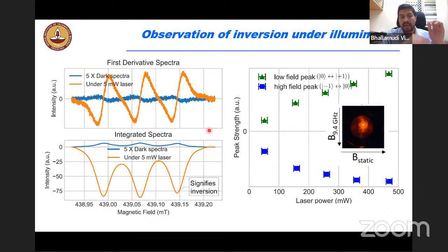And usually in that graph, the NV would be approaching very good. And the state of the art, recently done by people at Delft University, Tim Taminiau's group, is 27 atom imaging using NV centers. So these are nuclei near the NV. So you're actually mapping nuclei using the NV centers. This is the state of the art for nanoscale MRI. And this is being done at room temperature and in ambient conditions. So if you combine the idea of working conditions, I think nothing comes close to it.